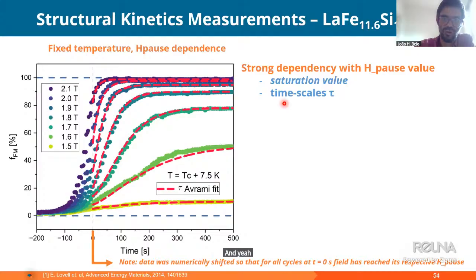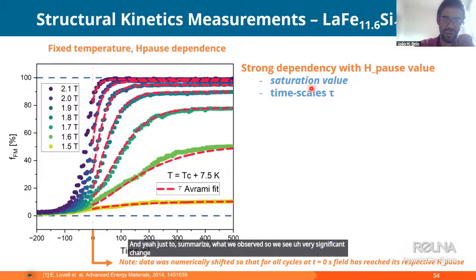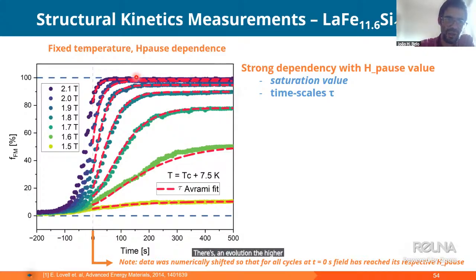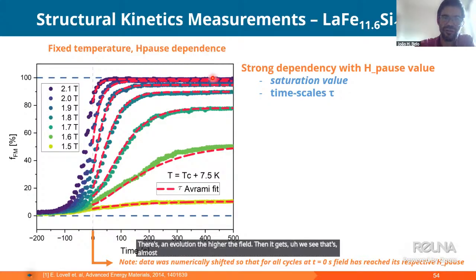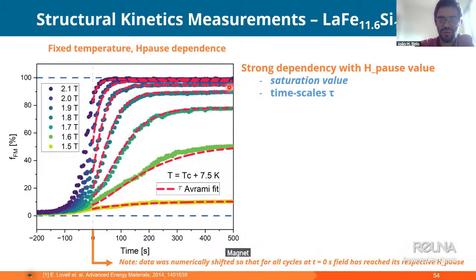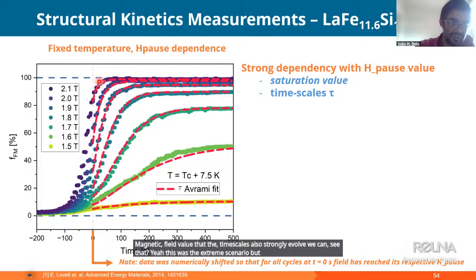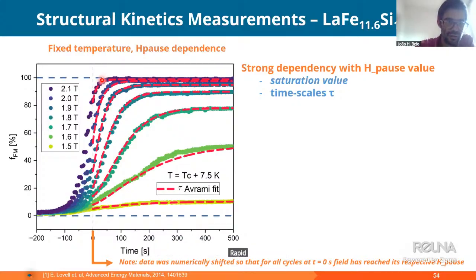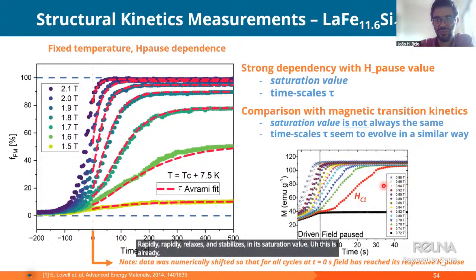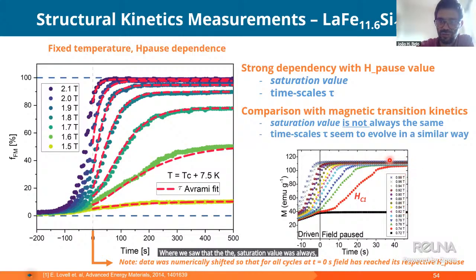And yeah, just to summarize what we observed, we see a very significant change in the saturation value, in the sense that they do not always saturate at the same value. There's an evolution. The higher the field, we see that almost all curves saturate at the same value after a given magnetic field value. The time scales also strongly evolve. This was the extreme scenario, but in contrast, this 2.1 Tesla curve rapidly relaxes and stabilizes at its saturation value. This is already different from what Edmond Lovell found out for the magnetic counterpart, where the saturation value was always the same for the different H-pause intensities. On the other hand, the timescales do seem to evolve in a similar way.